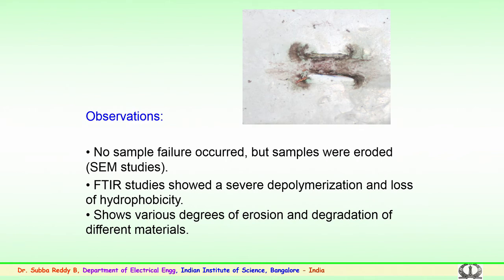This was observed after the experimentation, and the studies also showed various degrees of erosion; the depth of erosion and the changes on the surface were different for different types of materials which have been used. We have tried to use several types of materials including the liquid silicon rubber. So, the degradation was different for different types of materials in this study. So, this is one of the experiments which was conducted. A similar thing is observed in the